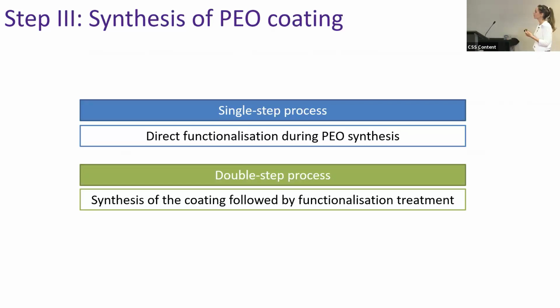So in this process, we are going to try to achieve the direct functionalization of the coating while the coating is being synthesized. This is a little bit more risky because the coating growth is assisted by plasma microdischarges. And these microdischarges might destroy the 3D integrity of my nanocontainers. The second option is to synthesize the coating in the first step and functionalize it afterwards in a post-treatment.